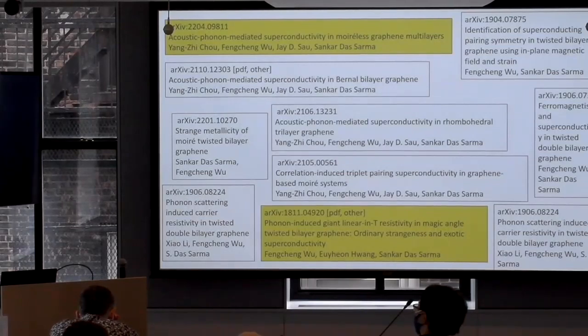But I have this feeling, having done a lot of electron phonon calculations, that not everything can be explained by electron phonon. Now, Steve Kivelson tells me that he also thinks electron phonon may play a role. The real mystery is that you have many, many phonons. There are like 5 different atoms in the unit cell. Why is the slope always the same? You think there should be little kinks. And so he thinks some kind of large N theory can resolve that. I have not thought deeply about it. So all I'm saying is a precise statement.